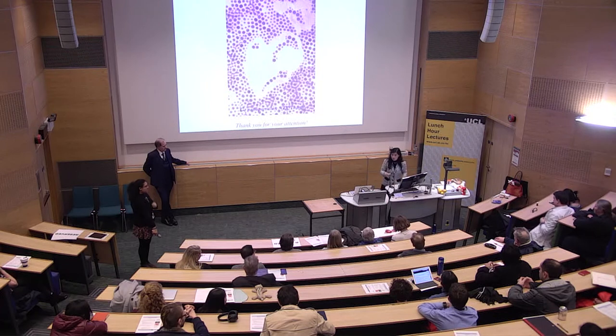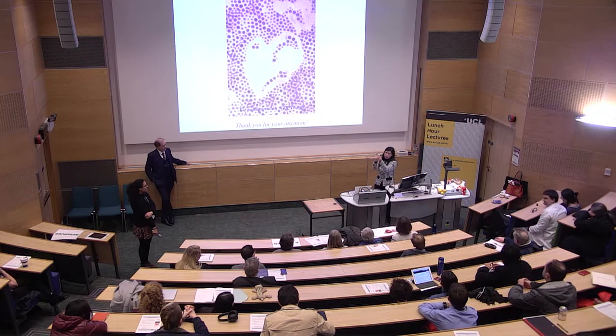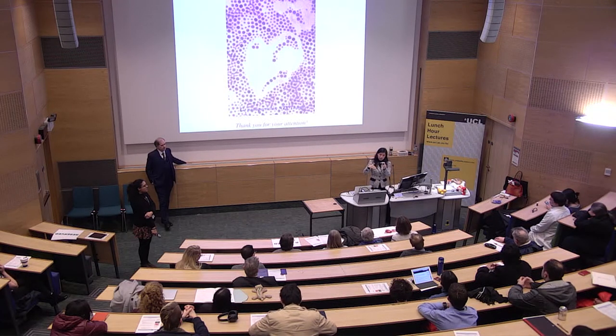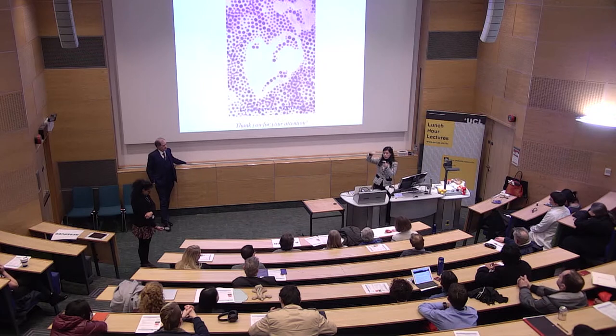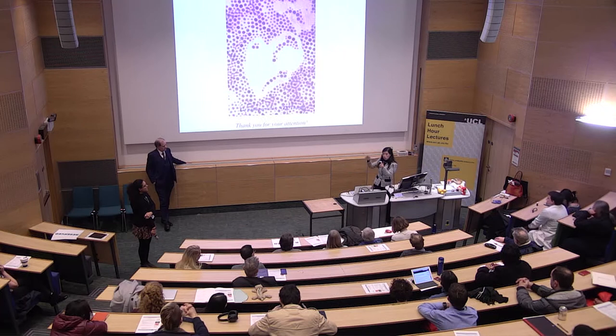Now if you have a rod, the light interacts in that direction, horizontal, even with that. So you can see now it dampens the peak at 520, you see a very, very little peak, but you get a very strong peak at the longer wavelength. So it shifts the peak to the near infrared and it absorbs very strongly there.